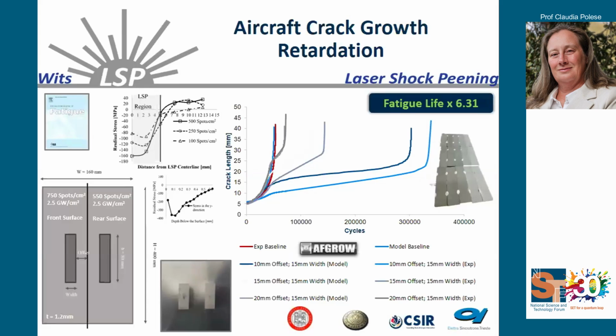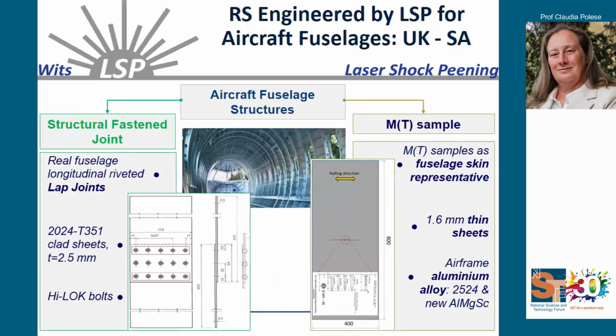and you use that specific airframe component within different intervals for maintenance. So here is one of the first works that we did, trying to use laser shock peening, introducing almost patches or stripes of laser shock peening in critical areas. And we increased what we call the fatigue life six times. So a really, really good result.